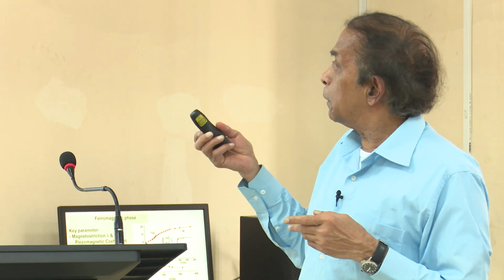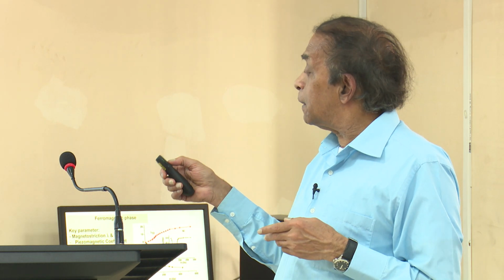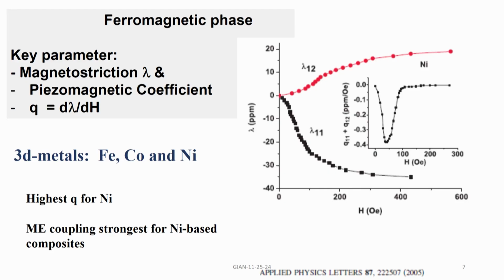Okay. So, as we see here, lambda 11 is negative and lambda 12 is positive, and usually it is 1/2 of lambda 11. The maximum value here is 15 and the maximum value for lambda 11 is 30. It is 1/2 of that. That is always the case, but there may be some departure here and there, but the rule of thumb is lambda 11 is twice the magnitude of lambda 12 or lambda 13, but there is also a change in the sign.